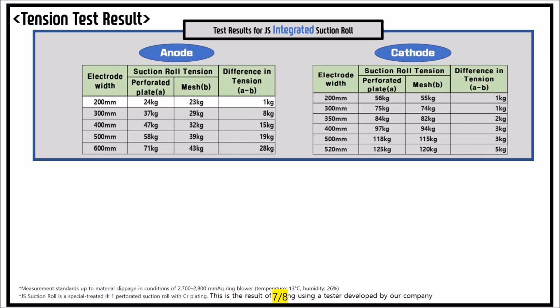To evaluate the tension of mesh-type and perforated-type suction rolls, we developed a specialized tension testing device and conducted a test. The test results are as follows. For the anode material, at an electrode width of 200 millimeters, the tension value of the perforated plate type that our company has developed was measured at 24 kilograms, which is 1 kilogram higher than the 23 kilograms of the mesh type. At 400 millimeters, the perforated plate showed a tension that was 15 kilograms higher than the mesh type. At 600 millimeters, its tension was 28 kilograms higher.